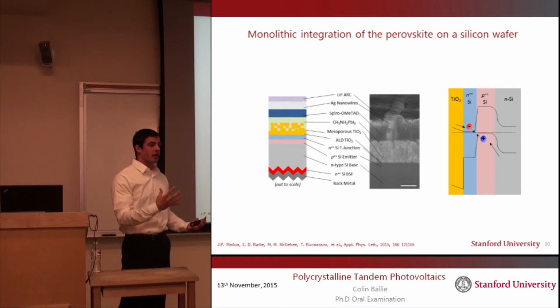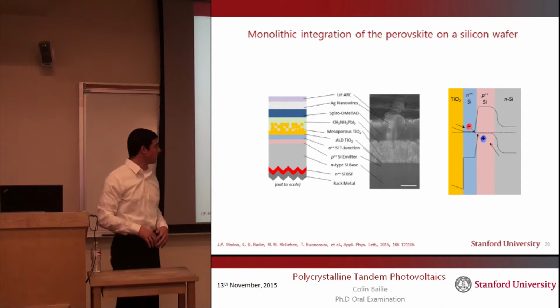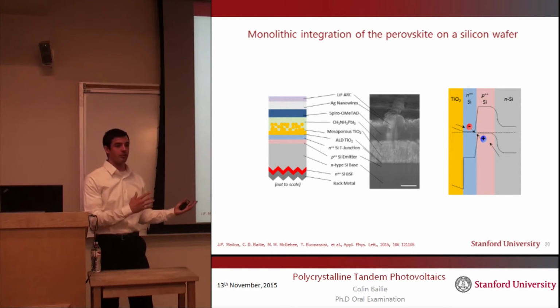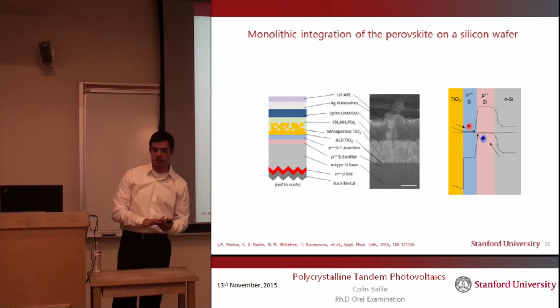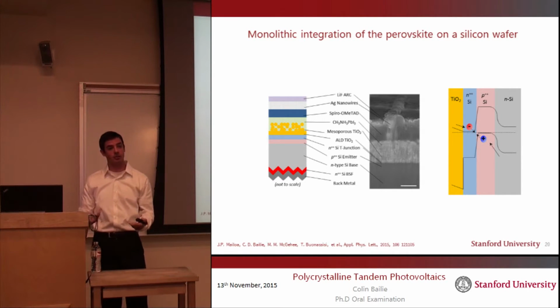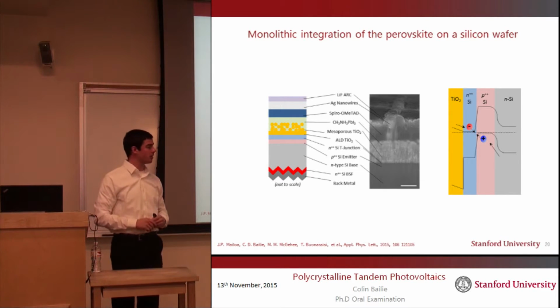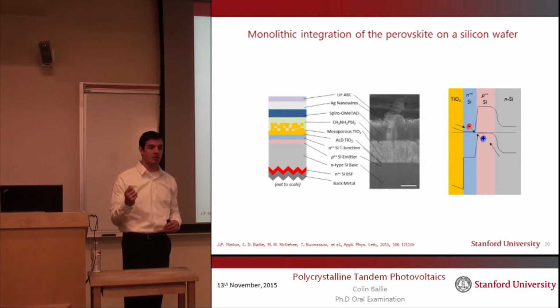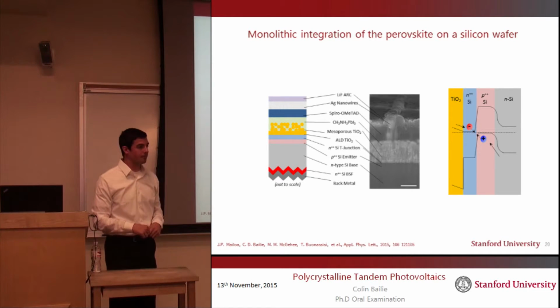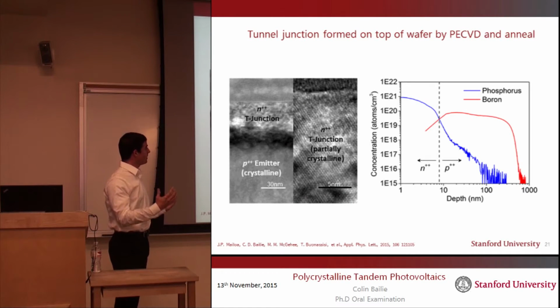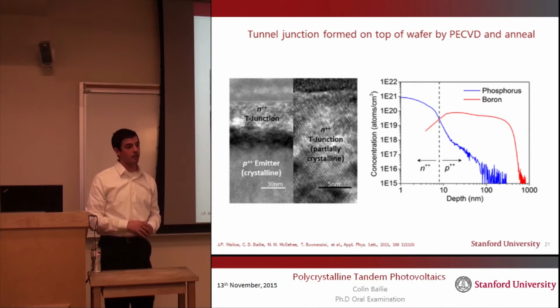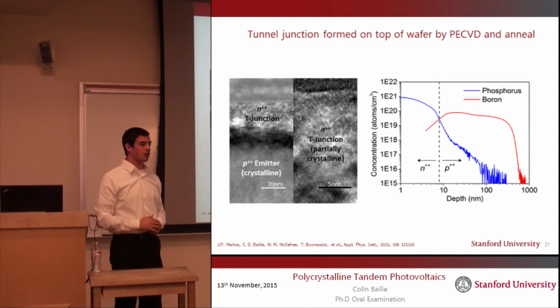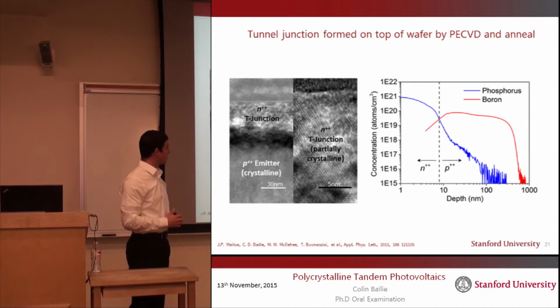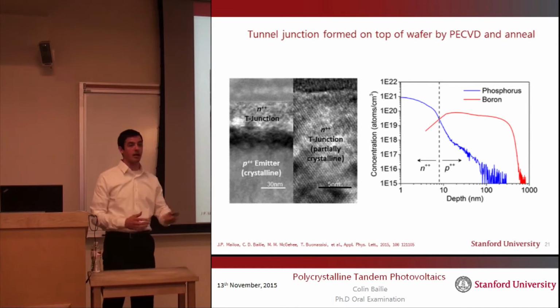We'll focus on the monolithic tandem first, and this was in collaboration with researchers out of MIT. We decided to take an N-type silicon wafer and do an ion implantation of the emitter, the P-type emitter, ending up with a classic PN silicon solar cell. And then by PECVD, we deposited an N-type amorphous layer on top and recrystallized it in order to form a tunneling junction in between this N-type layer and the emitter.